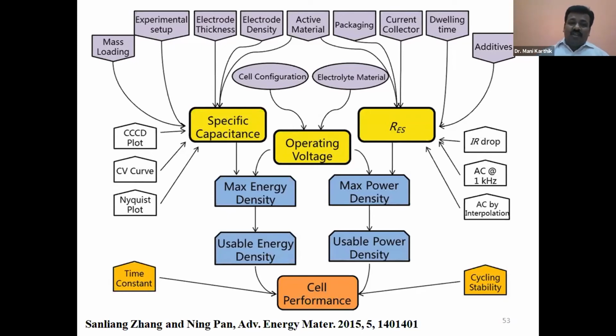So in this case, there are a lot of things involved from the commercial perspective, not lab, because most of the students are coming, I am cutting one gram or 1 milligram or 2 milligrams, and we are getting really very high performance, but they are calculating in farads per gram. So they are coating in milligrams, then converting into grams. So there is a lot of error in the measurements and experimental conditions, so they are misleading the results finally. So my advice is, anyway, this is very tough, but we need to go for more material loading, and we need to go for more reality value to the state of the art.